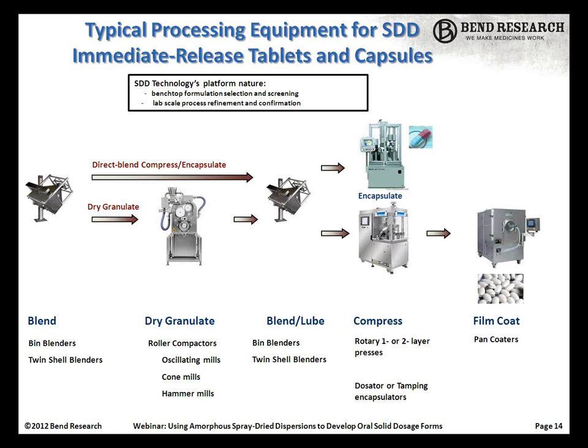Additionally, both the dry granulation and the direct compression processes shown here are continuous unit operations that are very useful and easily scalable. If you notice, this is really not any different than if this were an immediate release non-solid dispersion API. Bin blenders, twin shell blenders are typically used. Roller compactors or direct compression, and then encapsulation, either standard or bilayer tablet presses, or standard tamping or dosator encapsulators. One thing to note is that aqueous film coating is something we do very routinely. The dispersions are stable enough to withstand the aqueous coating environment.